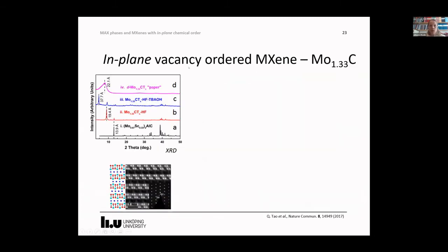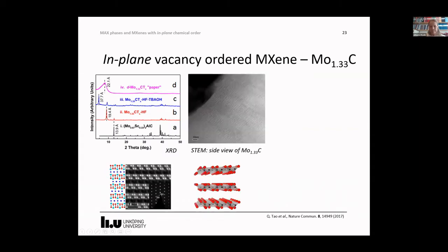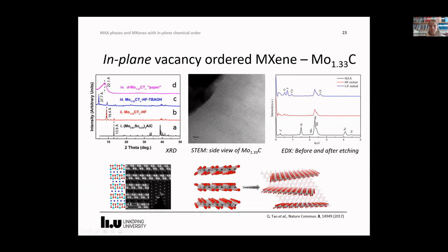Yes, and the first vacancy MXene we synthesized was Mo1.33C from the molybdenum scandium aluminium carbide. Here you see an XRD of the MAX phase and the MXene formed after etching. Here is a schematic of the multilayer MXene after etching, and this is the corresponding TEM image that shows multilayers, but there is no aluminium remaining.